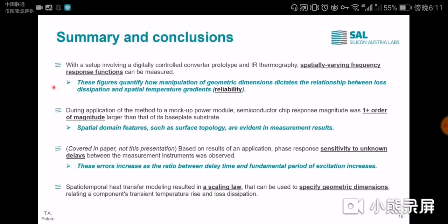And these are telling us in a detailed way how geometric dimensions dictate the relationship between the loss dissipation in our devices and spatial temperature gradients. Keyword here is reliability. We were able to see features or magnitude responses that varied on the order of at least one order of magnitude, depending if we were on the semiconductor chip or on the base plate substrate.